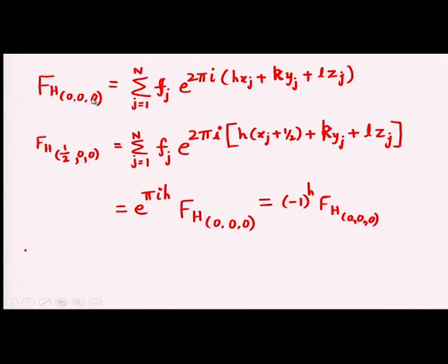So, by knowing a limited number of reflections chosen for origin fixing and one reflection for enantiomorph fixing, we can phase the rest of the reflections with the knowledge of these 4 reflections. Each origin fixing reflection can have a phase value 0 or pi, and the enantiomorph fixing one will have plus or minus pi by 2.